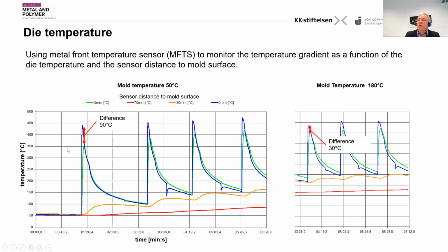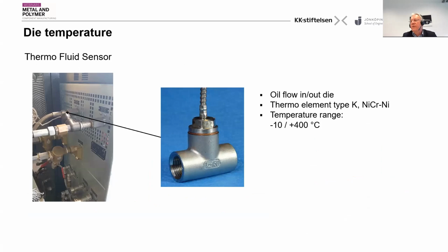The die temperatures are, of course, very much controlled by tempering oil. You have oil cooling and heating systems close to the machine, to the die, and you set them to 50 degrees or 180 degrees, and you assume the die will, after a certain time, also have 180 degrees. But nobody really controls the flow. Is oil really flowing into it? And I think this is a very inexpensive, very usable tool to control oil flow, not only temperature, but the flow rate.